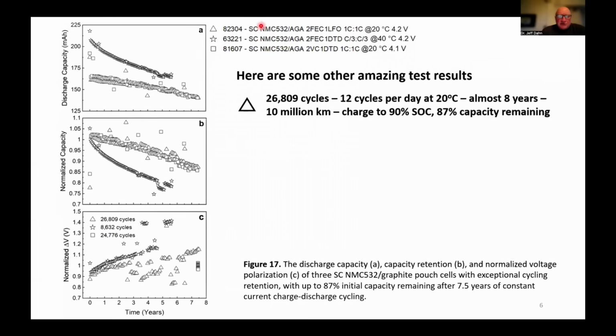So let's talk about the triangle data first. The triangles you can see here, you plot the discharge capacity versus testing time in years. And in the middle graph, we show the normalized capacity. So it starts with a fractional capacity of 1. And after almost 8 years and 26,000 cycles, it has 87% capacity remaining.